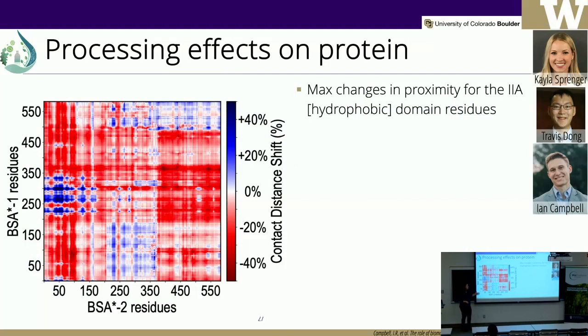First of all, what's happening to the conformation of our protein. So here you see a heat map. This is a residue map. You see the first molecule and the second molecule, and you see which of the residues of your protein come closer together, those are going to be in the red color. And the ones in blue are the amino acid sequences that are pushed further apart as you hot press the material. So you do see systematic changes.